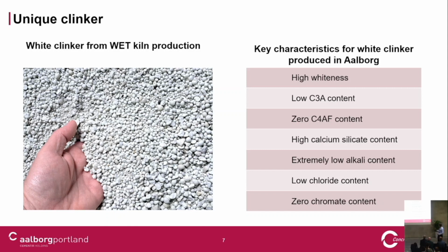This gives us high whiteness. We have a very low C3A content, that's possible because of the technique. So we have a sulfate-resistant cement. Of course, we have zero iron phase - otherwise, we will not be white.